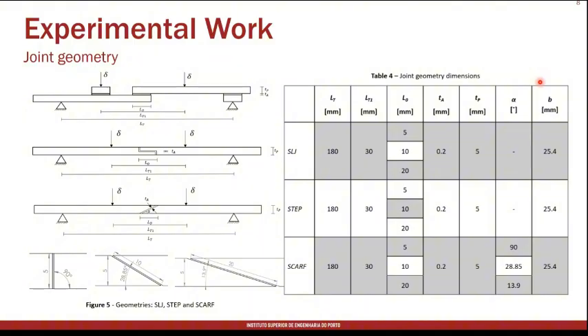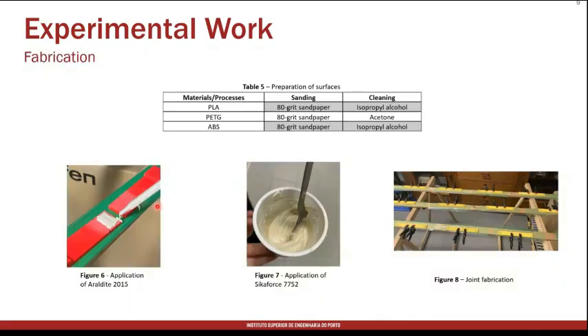We tested 3 geometries under 4-point bending. We can see here all of the dimensions that we tested, and here the main parameter that is varied in the 3 types of joints is the overlap length, basically the length of adhesive between the 2 adherents, and this was varied in values of 5 millimeters, 10 millimeters, and 20 millimeters.